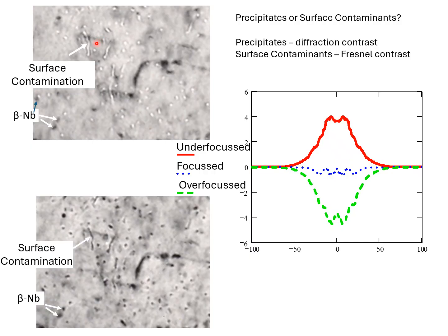And we have the same Fresnel contrast, and you can see that this isn't a cavity, it's a little string of something, a little wormy structure. These wormy structures exist from the contamination and would show up bright or dark, depending. Now, the more circular ones, which you might mistake for a cavity, also show up in the same vein as bright or dark. Now, the reason that there are two points here.